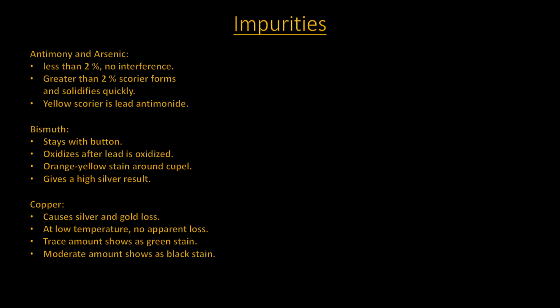Gold and silver loss will not be apparent at lower cupellation temperature. At higher temperatures, almost all of the copper can be eliminated, but gold and silver losses will occur due to the increase in absorption of the cupel. Trace amounts of copper will present itself as a green stain on the cupel, but if there is a small to moderate amount, the staining will be black and there will be minute amounts still alloyed in the doré bead. Large amounts of copper present will actually flatten the bead out, giving it a coppery color. It may even cause the bead to freeze.